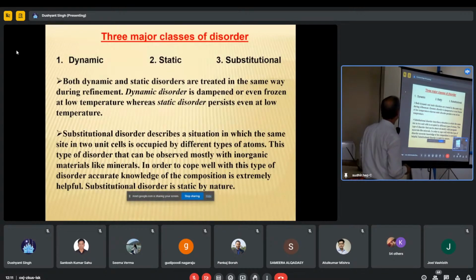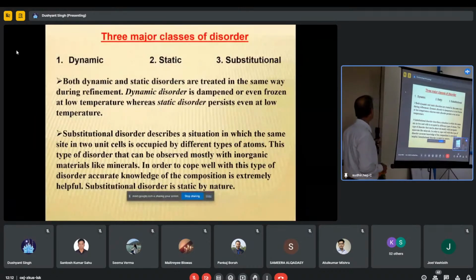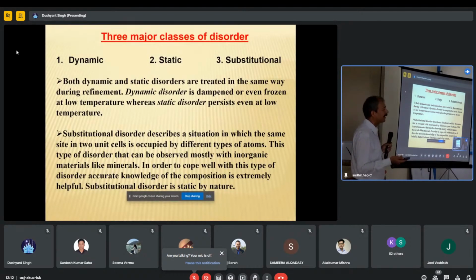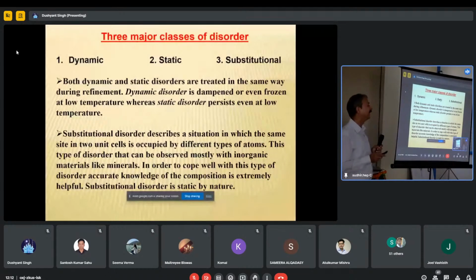A situation in which the same site in the two unit cells is occupied by different types of atoms. This type of disorder can be observed mostly with inorganic materials like minerals. So in order to cope well with this type of disorder, accurate knowledge of composition is very, very important. If you don't know whether the substituent is chlorine or some other, like sulfur, you should have some basic idea. Even from the shape of the ellipsoid, we can make out whether it is a low atomic number atom or a high atomic number atom. If you assign carbon as oxygen or oxygen as carbon, the ellipsoid will be very, very small or very, very large.